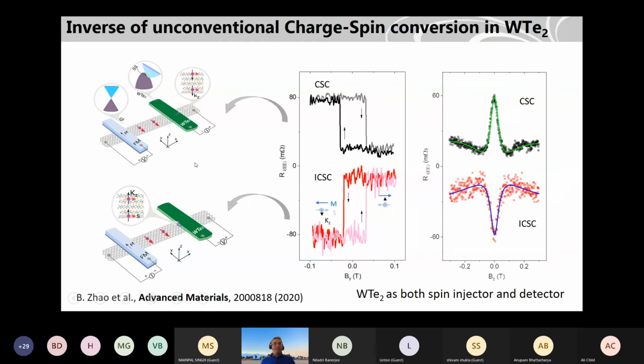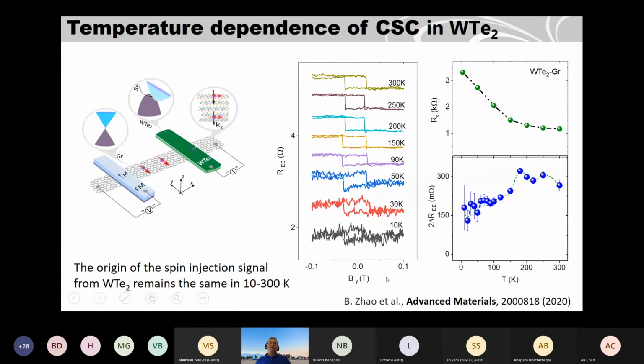So in addition to the injection of spin from tungsten telluride, we can use the tungsten telluride also to detect the spin. So we send a spin current from the ferromagnet into graphene and it enters tungsten telluride, and tungsten telluride detects a voltage, which actually detects the spin as you see here. Both signals are reciprocal to each other, and even the Hanle signals also survive.